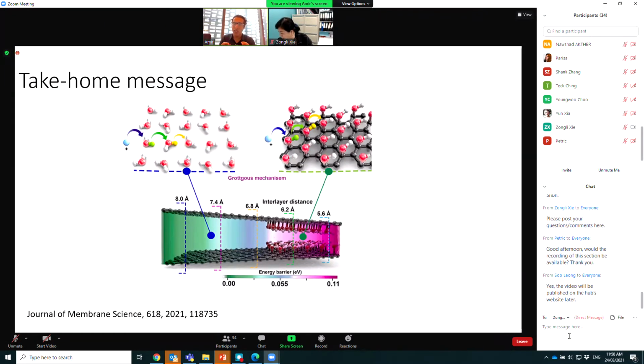By manipulating the chemistry and morphology of your membrane, you put in the asymmetrical element: asymmetry in chemistry, asymmetry in morphology, or wettability. You can create asymmetrical energy barriers across the membrane, and that gives you an opportunity to manipulate the ion transport rates of your elements and ions.